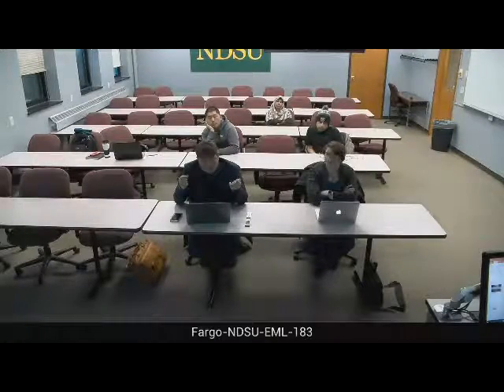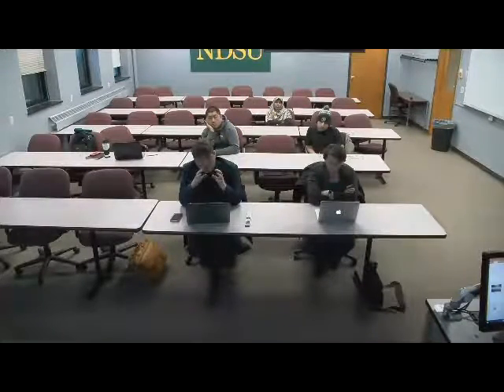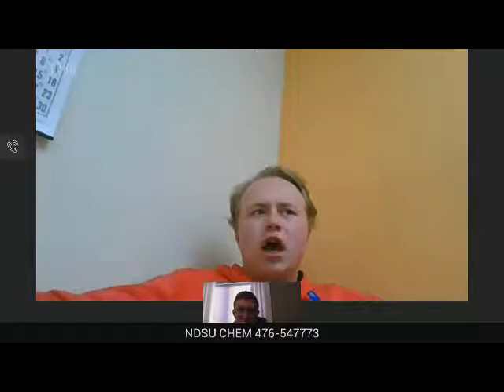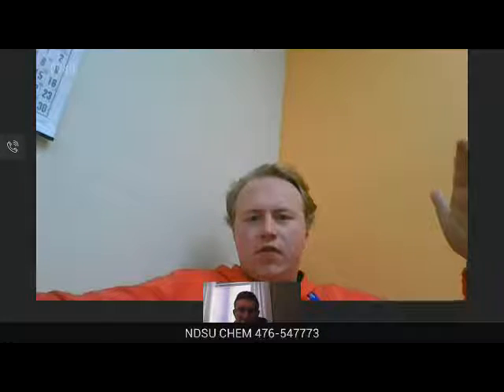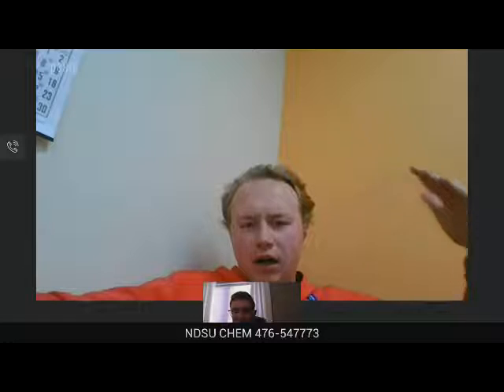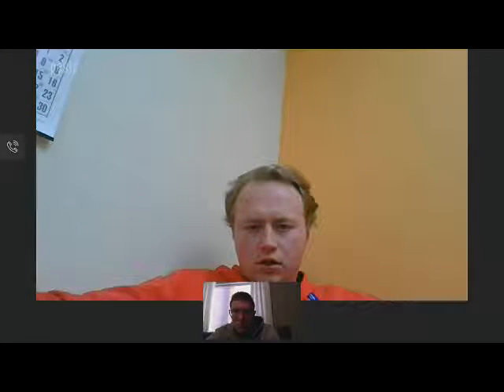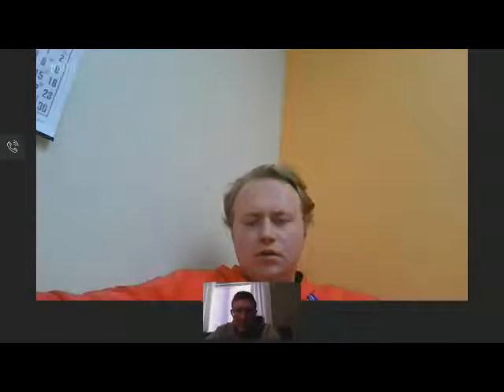Yes, correct. And on the other hand, the ligands in the system that Aaron has presented try to mimic the symmetry of a crystal a little away from the crystal. So they keep the same coordination for each surface ion. In other words, you're saying that these ligands try to reduce the influence of the interface between the quantum dot and the ligands, and the rest of the environment around the quantum dot. Yes.